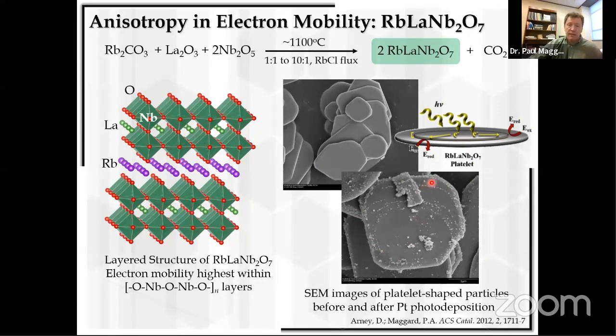This highlights the fact that as your light is hitting the material and exciting the electrons, those electrons have mobility within the plane until they hit a little step edge, until they reach that outer edge where they can drive that surface reaction. And so similarly, when you're driving water reduction to hydrogen, the more step edges you have, the higher the rate. This is basically where the reaction is occurring.